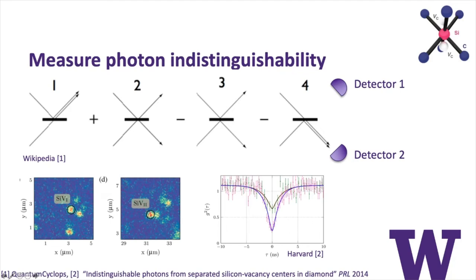The top gets reflected, the bottom gets transmitted; they both get transmitted; they both get reflected; or the top gets transmitted and the bottom gets reflected. There is a phase associated with each one of these, and it turns out that the middle two have opposite signs, and so they cancel out, but only if the photons are indistinguishable. In the case of indistinguishable photons, you can only get two photons coming out to detector one, or two photons coming out to detector two, and you should never get a coincidence between these two. And what you observe experimentally, this is an example from the SiV center in diamond, is that, using G2 now on two different centers, it goes down.